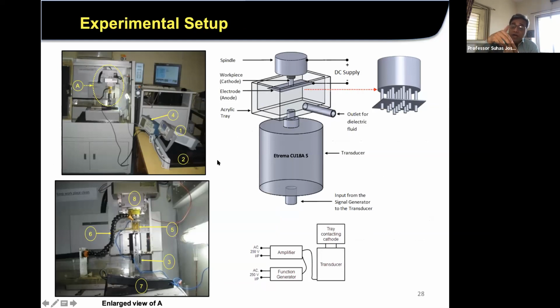We found that during the process, as the electrodes and rods move up and down, the debris which gets accumulated around the holes sticks to the rods and keeps on eroding them. So the rods formed in softer metals are not very straight, and they have a lot of constrictions and uneven surfaces. So we came up with the idea: why don't we provide some kind of vibration motion to the table itself? When this vibration motion is provided, the debris particles actually get away from the whole process.